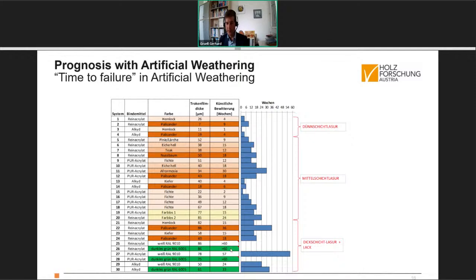But there are still 3 systems which were not degraded so far during 60 weeks. So we gave up in the end and said that's enough. So 3 systems remained which were more durable than 60 weeks of artificial weathering. And these 3 systems were all 3 opaque coating systems, whereas the transparent systems have reached the limit state earlier.